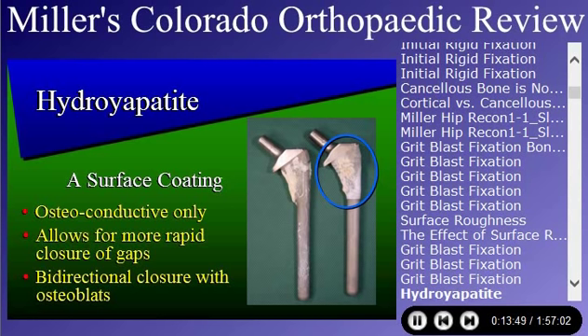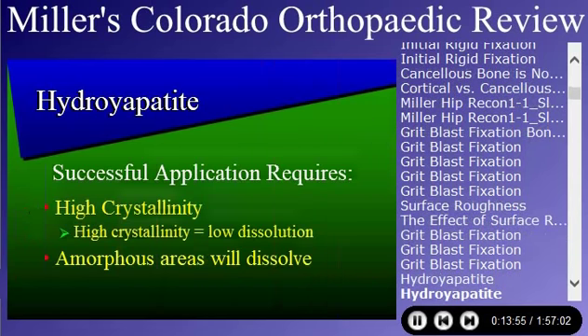So you have a bidirectional closure of gaps, and so your fixation is stronger and quicker, but in the long term, nobody's really shown that it's provided any stronger fixation than just porous coating alone. The success, though, if for test questions, is what you need is high crystallinity. If you have high crystallinity, you have low dissolution. If you have amorphous areas, those areas dissolve and then the HA falls apart. So high crystallinity and avoid the amorphous areas.